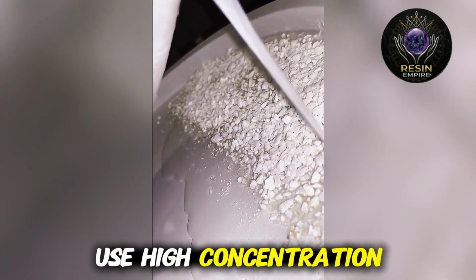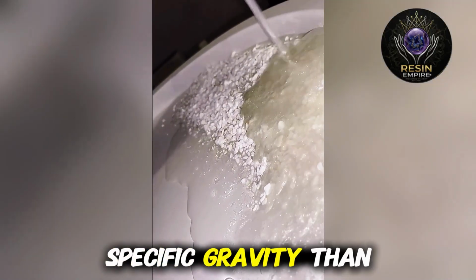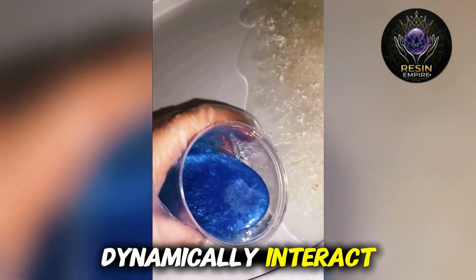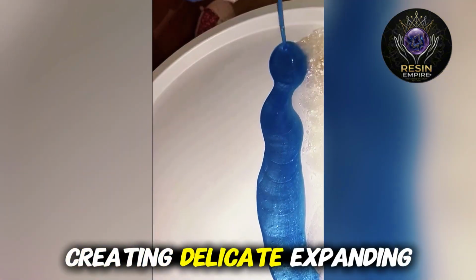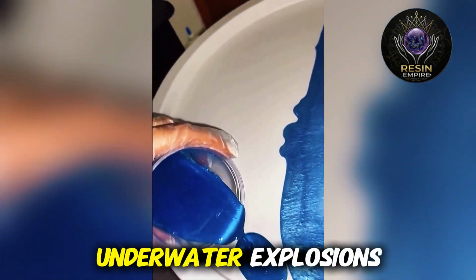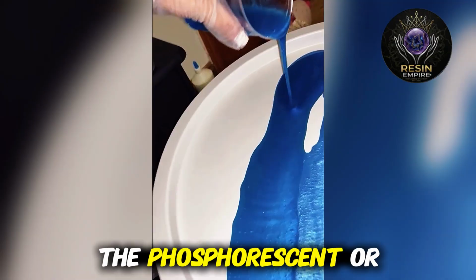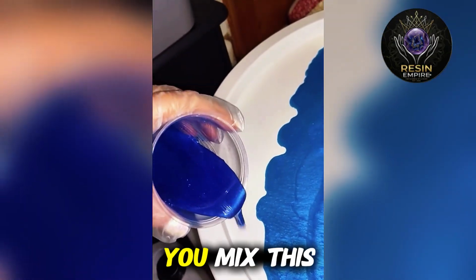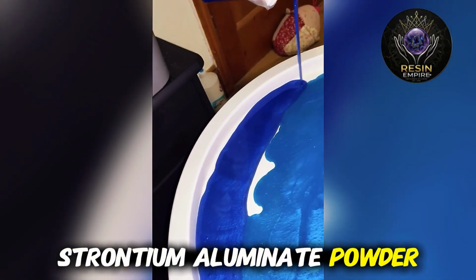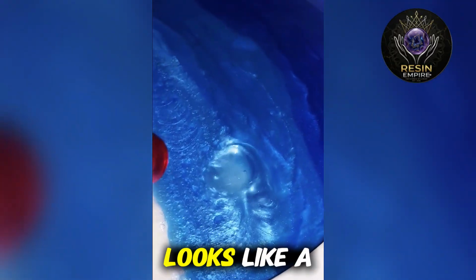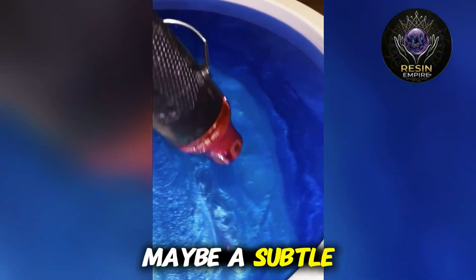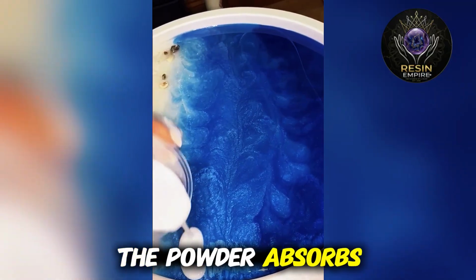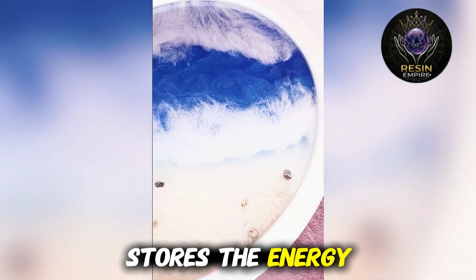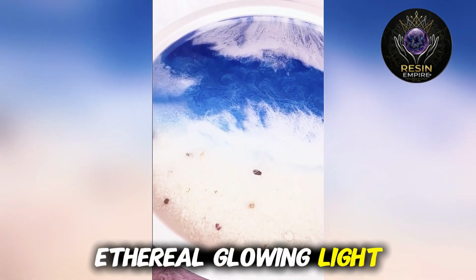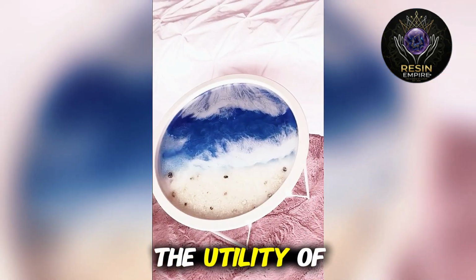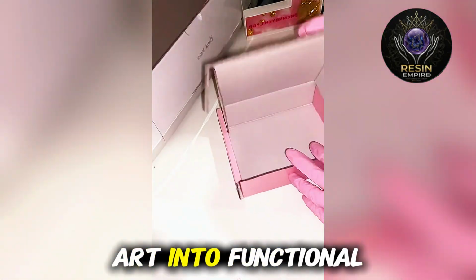Yes. They also use high-concentration alcohol inks, which possess a different specific gravity than the resin, allowing them to dynamically interact and push through the fluid, creating delicate, expanding blooms of translucent color that look like underwater explosions. And my absolute favorite, the phosphorescent or glow powders. Those are incredibly popular. You mix this rare earth strontium aluminate powder into the resin, and during the day, the piece looks like a sophisticated clear sculpture with maybe a subtle milky hue. But at night, the powder absorbs the ambient ultraviolet daylight, stores the energy, and emits this soft, ethereal, glowing light for hours. And it's beautiful. You fundamentally change the utility of the object. You turn a static piece of art into functional ambient lighting.